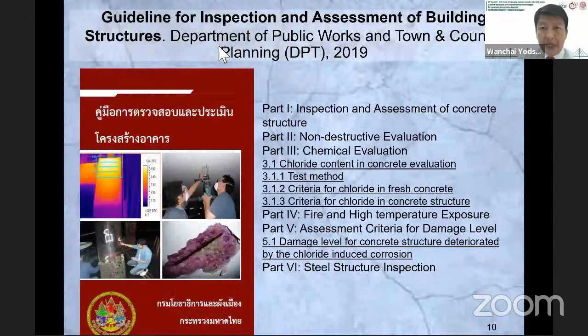The next one, within this standard, the DPT also has the guideline for inspection and assessment of building structure with the same standard. With this standard, we have the guideline together. In the guideline part three, we have chemical evaluation, that is the chloride content in concrete evaluation. We have the test method, criteria for chloride in fresh concrete, and criteria for chloride in concrete structure. And in part four, we have assessment criteria for damage level of concrete structure deteriorated by chloride-induced corrosion.